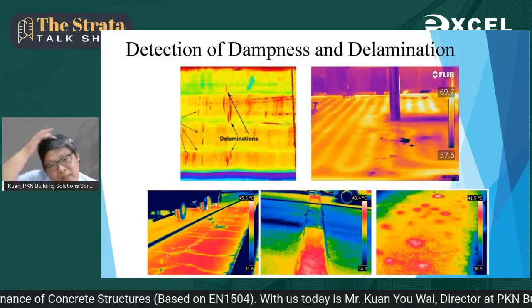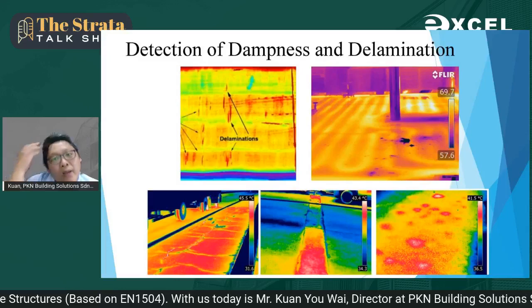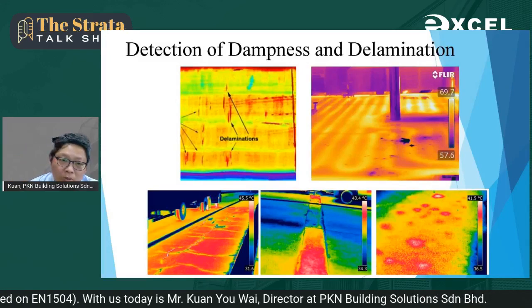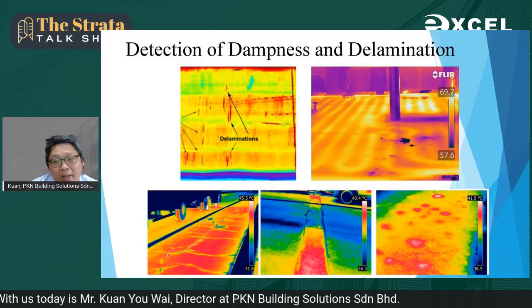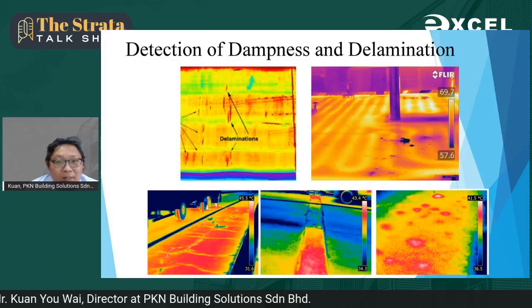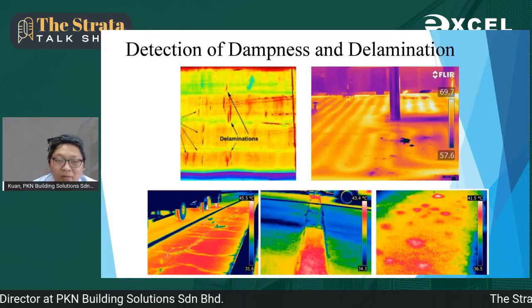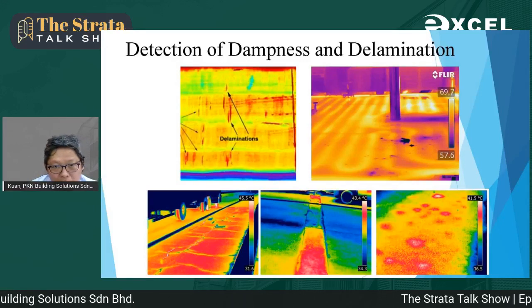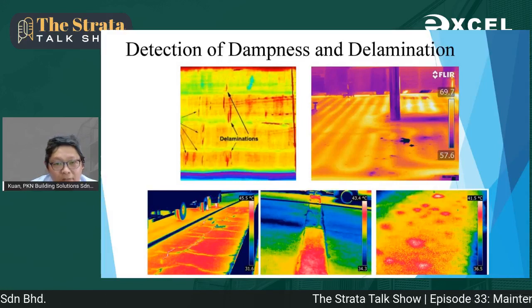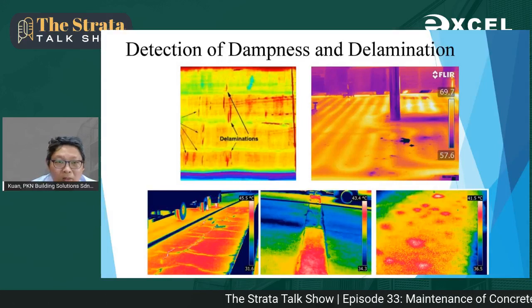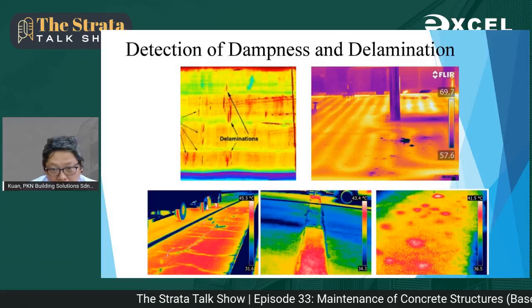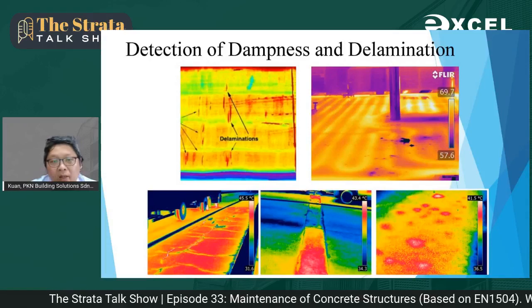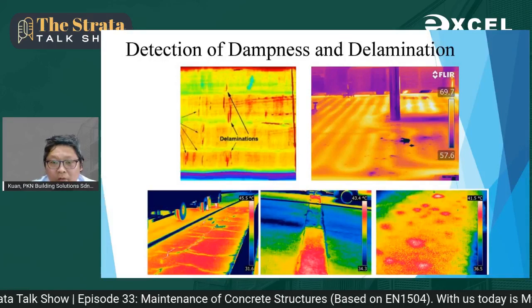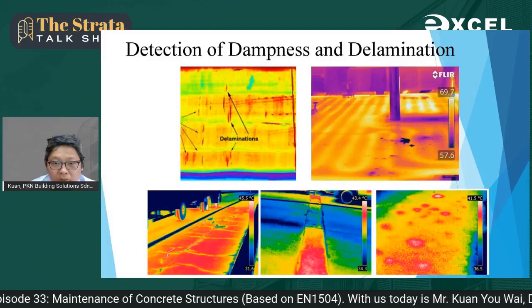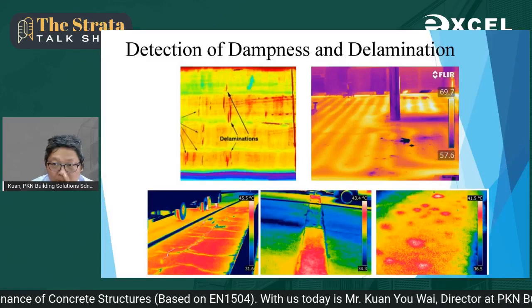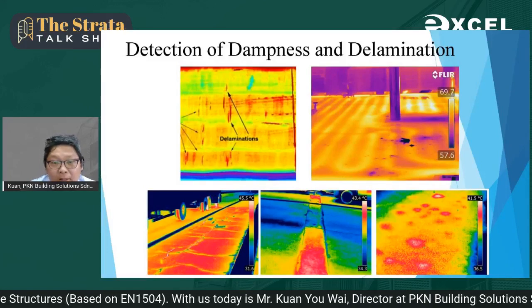Once there is delamination or crack, any diffusion of water or air into the concrete can be identified easily with infrared imaging. The first photo shows the infrared imaging on the wall, and the photo at the bottom shows the infrared imaging for the flat roof. So it can be identified based on the understanding of infrared and the property of water.